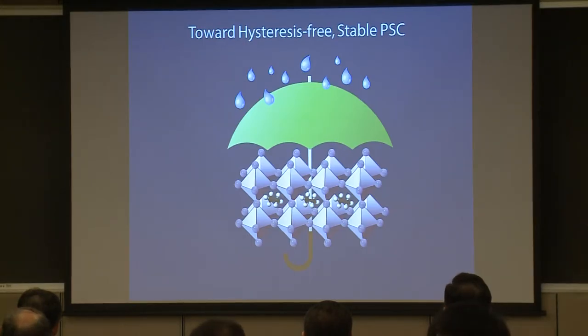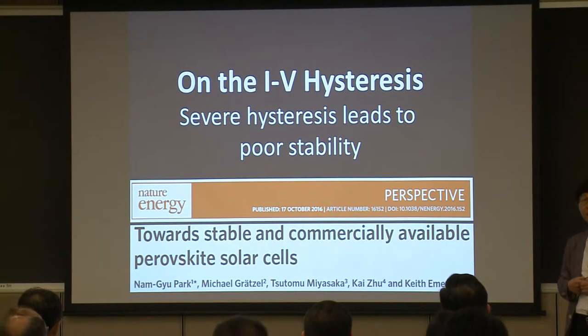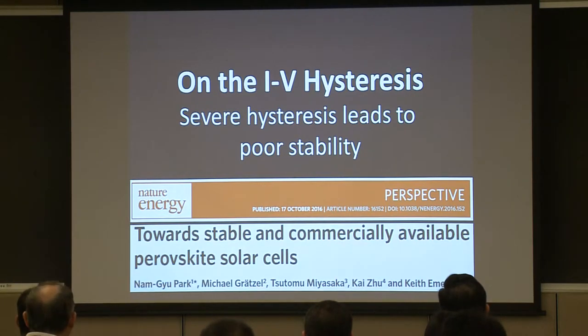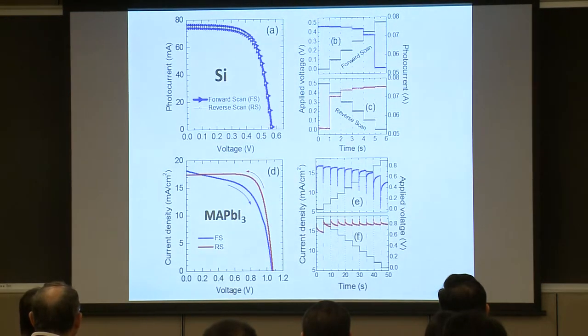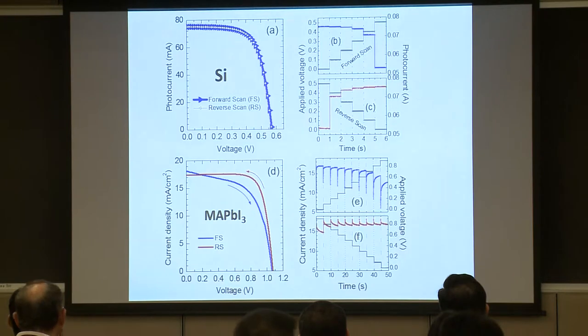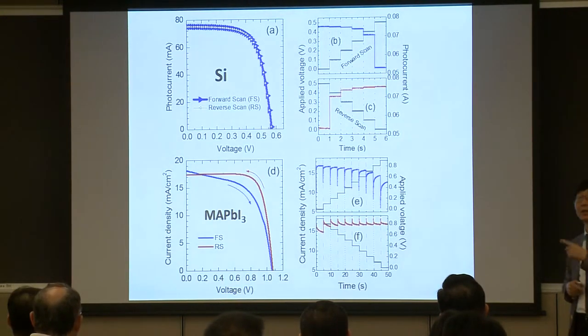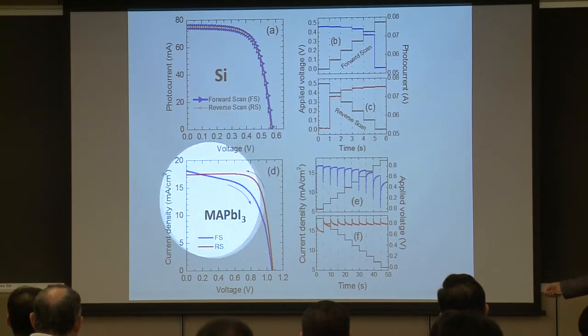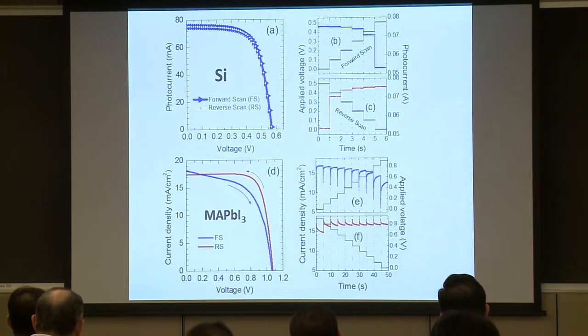Let me move on to some technology issues in the perovskite solar cell. The perovskite solar cell has been suffering from the hysteresis issue and also stability. Stability and hysteresis are correlated. So toward a hysteresis-free and stable perovskite solar cell, we need some strategy for interfacial engineering or defect engineering. First, hysteresis: for instance, in a silicon type solar cell, we don't see any hysteresis. Hysteresis means some kind of mismatch between the forward scan IV curve and the reverse scan IV curve. But with methyl ammonium lead iodide, we can see a very severe IV hysteresis. Between the reverse scan and forward scan, you have a big difference in the IV curve.